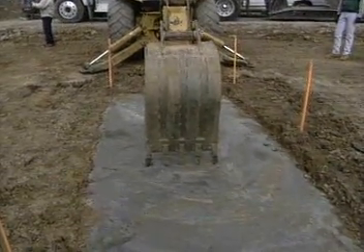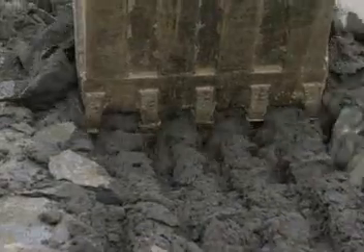Excavatable flowable fill has been defined by the National Ready Mixed Concrete Association as having a maximum compressive strength of 150 pounds per square inch at 1 year. Strengths exceeding this limit have been known to be excavatable with the use of mechanical equipment. However, tests indicating the ease of excavatability should be made prior to final placement.